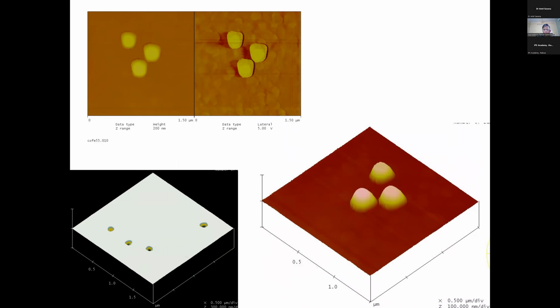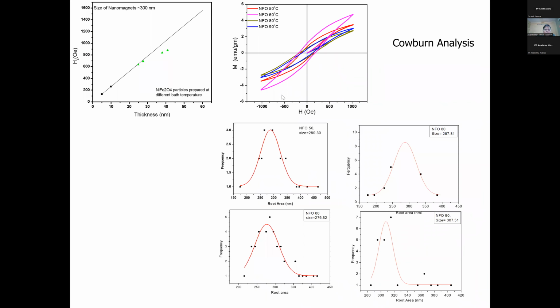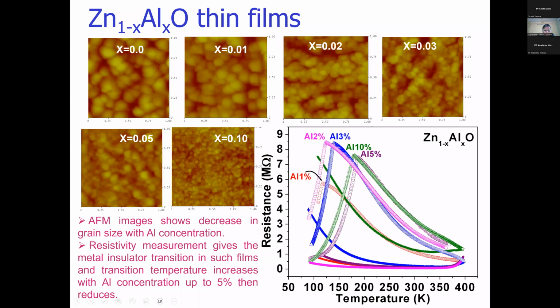It is a very difficult experiment because it's done on a powder. The powder also will move when the tip moves on it. That's very difficult. You need patience to do that. But then we did a magnetization also for that. Then we worked on a scaling called Cowburn scaling. How the coercivity behaves when the thickness is only 10 nanometer, 20 nanometer, 30 nanometer, 40 nanometer. After that, this scaling will deviate. This is very interesting. So this is something with respect to how different microstructures evolve.